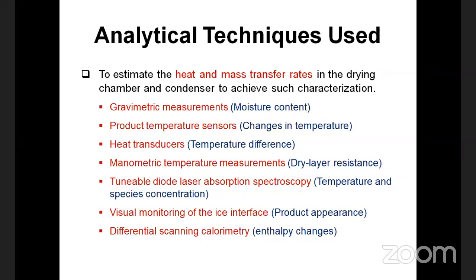There are different analytical techniques used since the freeze drying process has been developed. The prominent among them include gravimetric measurements, where moisture content is determined, and product temperature sensors, where change in temperature is determined, or the difference in temperature between the vapor in the chamber and the product. Then heat transducers are used to find out temperature differences. Manometric temperature measurements are also used, which use dry layer resistance. Then tunable diode laser absorption spectroscopy is also used, wherein the temperature and the concentration of solute in the formulation is determined, and visual monitoring of the ice interface, so that we can have a look at the product and continuously monitor it. And the most commonly used conventional method is DSC, where enthalpy changes are used as an indication of product critical temperature.